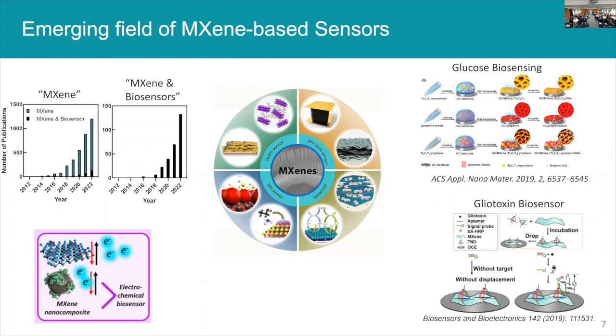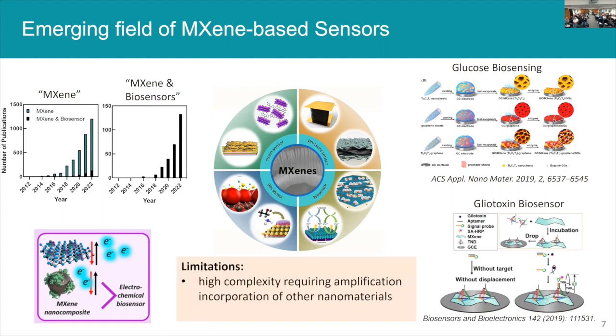So the first one is graphene plus MXene nanocomposite, and then they immobilize an enzyme, a glucose oxidase. The second one, to achieve enough sensitivity, they're having to add additional signal amplification steps by the use of HRP enzymes. So there's always either an enzyme or a nanocomposite material. And that we identify as a limitation that's increasing the complexity of their device. We've also noticed that there's limited robustness in these materials, and that the functionalization strategy is typically some type of physical adsorption between the bioreceptor, the oligo, or the antibody, and the material itself. There's also limited specificity in the choice of the materials.